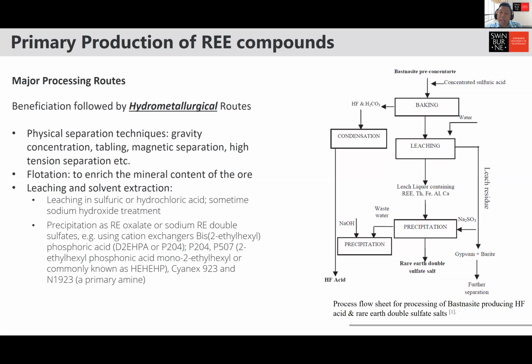And then we precipitate the rare earth elements using different precipitation solutions. For example, for the leaching itself, we can use sulfuric acid or hydrochloric acid. And in some processes, they also do a sodium hydroxide treatment to enhance the separation. After leaching, in the precipitation process, we form rare earth oxalate or sodium rare earth sulfates, basically using different types of cation exchanger, such as D2EHPA or P204. We can also use P507, or Cyanex 923, and other cation exchangers.